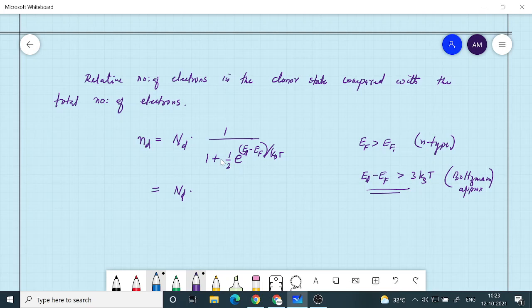Not if the doping concentration is very heavy, then of course this will be violated, but we are assuming that doping concentration is not to that extent. So we can write this as, if I take this term to the numerator, 2 into e raised to minus (Ed minus Ef) by kBT. So that is our Nd.